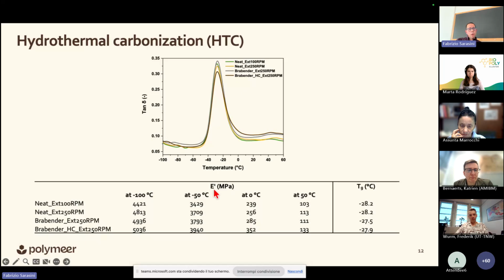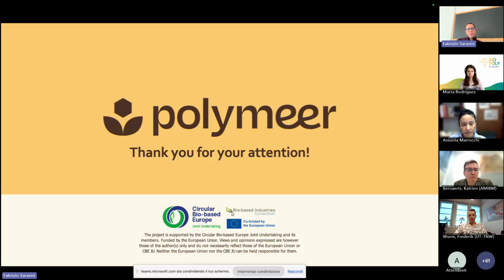And if you look at the evolution of storage modulus as a function of temperature, you can see that in this very broad range from -100 up to 50 Celsius degrees, the presence of hydrochar increased the storage modulus. So meaning that there is potential in using this filler, but this should be associated with careful optimization of the processing and also careful selection and design, engineering, I would say, of the biodegradable polymer blend. That's all from my side, and thank you for listening.